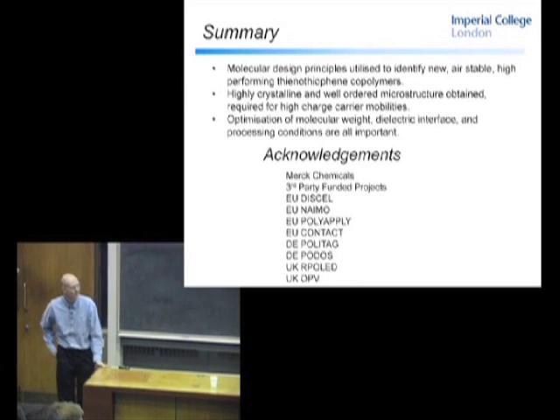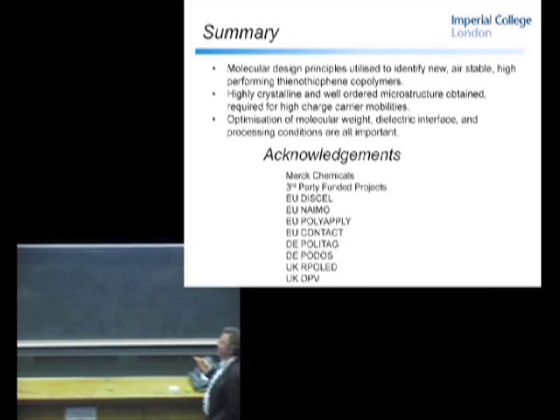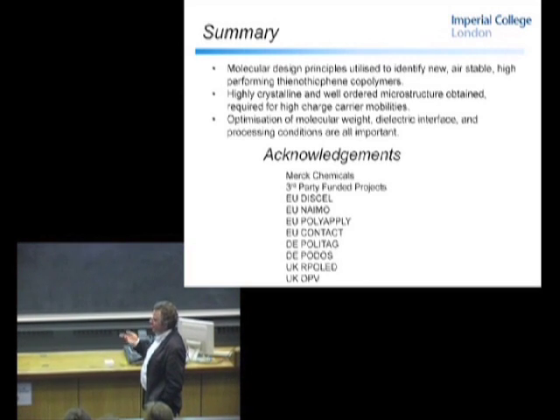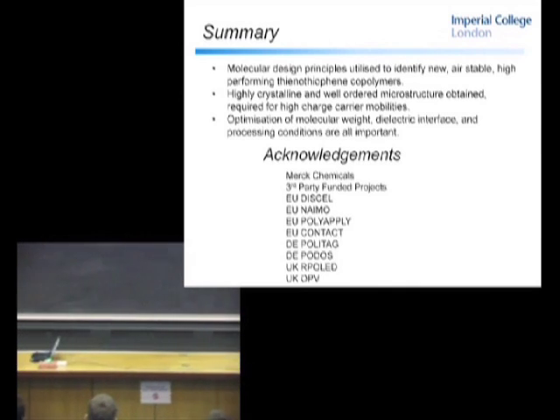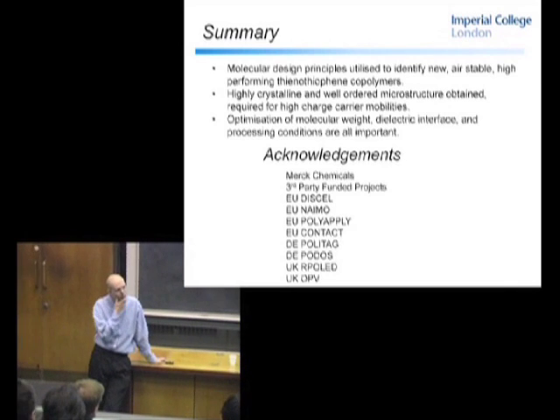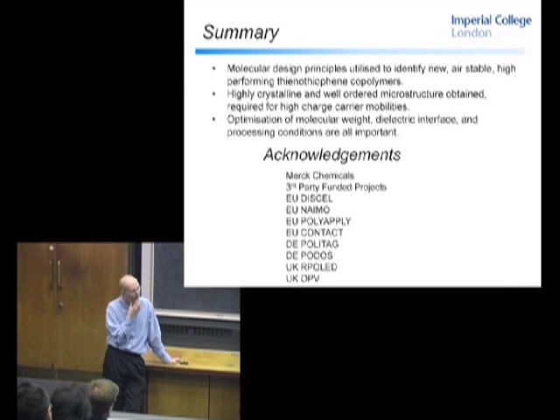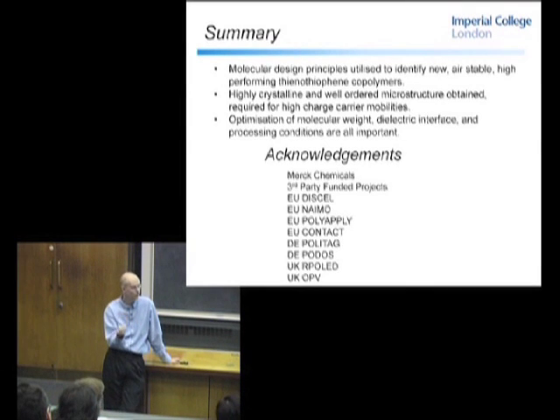Of course. The polymers that you've been describing, you talk about mobility all the time. Are we talking about intrinsic conductivity, and so basically electrons and holes here? No, this is field effect mobility, which is different, I guess, even from time of flight mobility in a couple of ways. One would maybe be the field dependence, and the other is the vector in which transport occurs. So I'm talking about in-plane two-dimensional transport at high field. Bulk transport, which you measure by time of flight, which is more important for OLED or photovoltaic devices, is an out-of-plane transport.